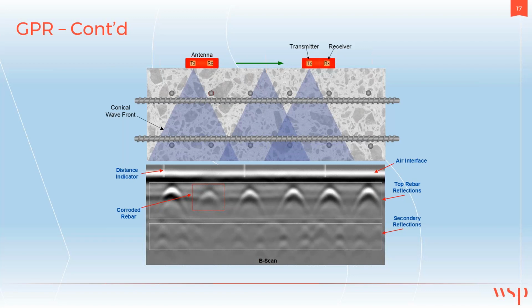The signal that is put into the concrete goes out in a conical shape. And so even though the information is interpreted as being vertical directly below the antenna, there's actually a conical range in which the signal is imparted. Those signals reflect off of changes in material through changes in what we call dielectric, and sharp changes in dielectric properties of two materials give higher contrast in the response.